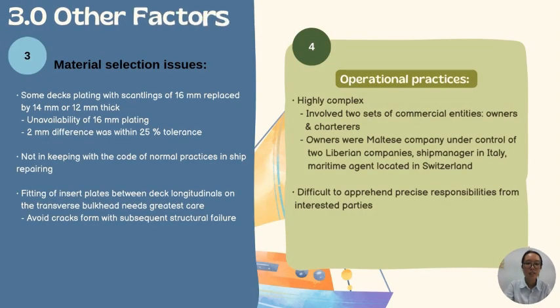The third factor is the material selection issue. Some plating with scantling of 16 mm was replaced by 14 or 12 mm due to its unavailability. This was supposedly accepted as it was within the 25% tolerance. However, such practice is not normal practice. The fitting of insert plates needs to be done with greater care, otherwise cracks may form and cause structural failure.